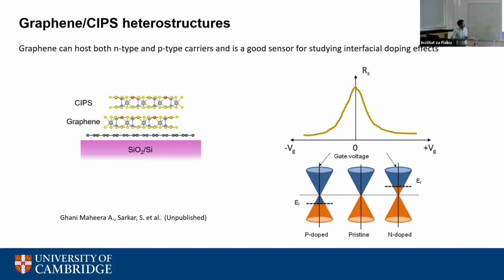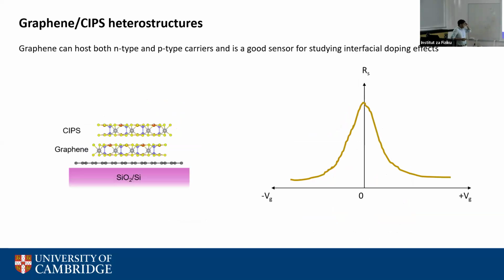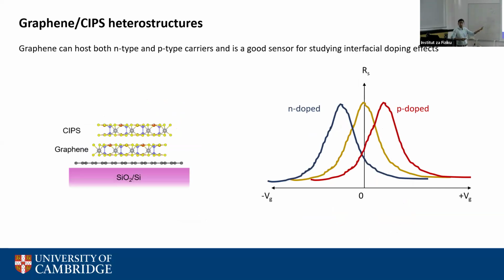And you can see that this is the electron doped region, this is the hole doped region. So if CIPS dopes graphene with electrons, you would see some changes in this resistivity versus gate voltage plot. To understand this, if you p-dope graphene, you would see the Dirac peak shift toward positive voltages. If you n-dope graphene, you would see the Dirac peak shift towards negative voltages. And we wanted to see what happens when we put CIPS on graphene.